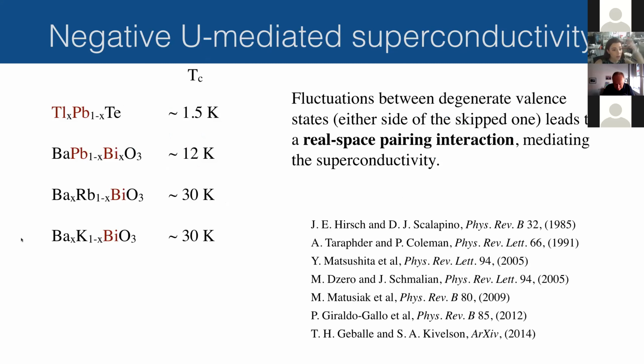So yeah, when you dope barium bismuthate, as well as some other negative U insulators, you quite easily find superconductivity. And the superconductivity is reasonably high temperature. Here is the famous BKBO superconductor. And the proposed mechanism underlying the superconductivity is that there is a real space pairing interaction between the two electrons that are sitting together, which is mediating superconductivity like a kind of Cooper pair. But crucially, they think that you have to have fluctuations. So you can't just have a complete pairing of electrons, because this would be probably an insulator.